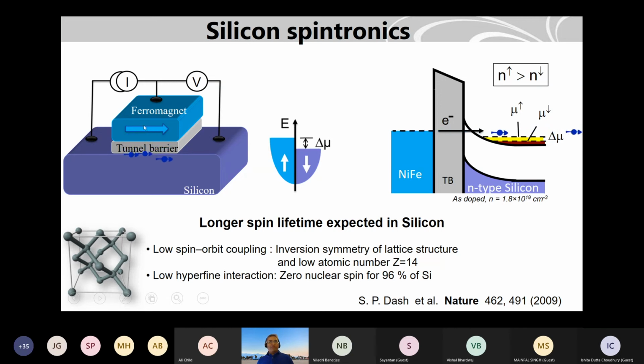So once you have this ferromagnet, you tunnel through this barrier and create spin polarization in silicon, and you create the spin splitting in silicon. So you have the ferromagnet, and you have this barrier. It can be aluminum oxide or magnesium oxide. You have this Schottky barrier, but you have to use highly doped silicon to keep it narrow, so electrons can go through. Then you create the spin splitting in silicon.